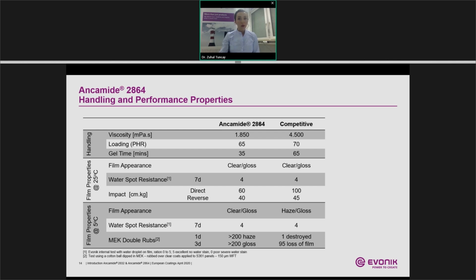Here we focus on performance properties of 2864 in comparison with high solid polyamide. As you can see, the initial viscosity of 2864 is lower. So it allows coating formulations with lower VOC for spray applications. For epoxy clear coat mixed and applied at 25 degrees, we see a shortening in gel time, which is to be expected. The surface appearance at that temperature is excellent. Impact resistance and water spot resistance are in line with the competitive system.